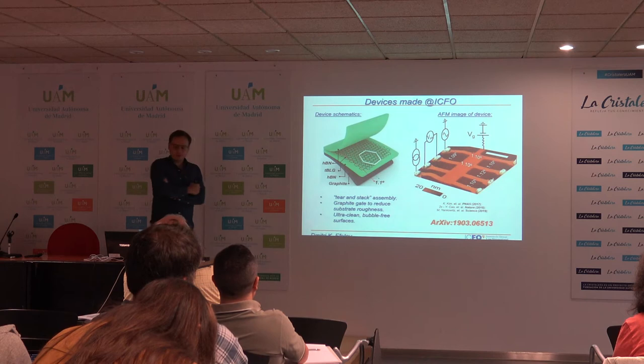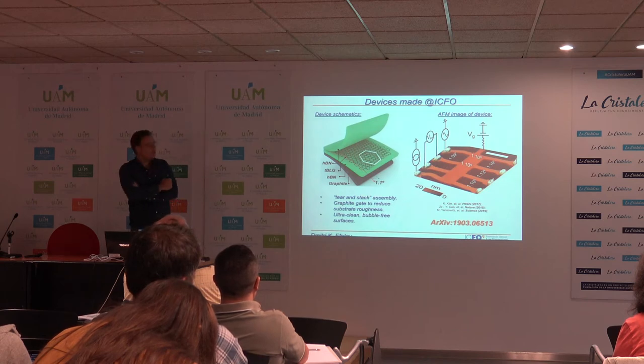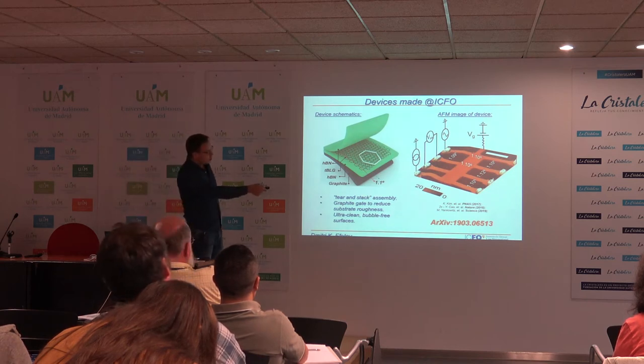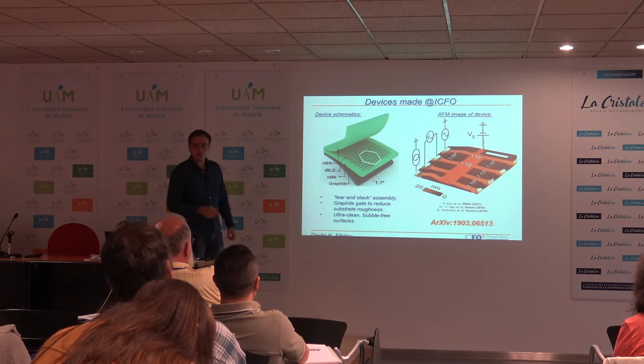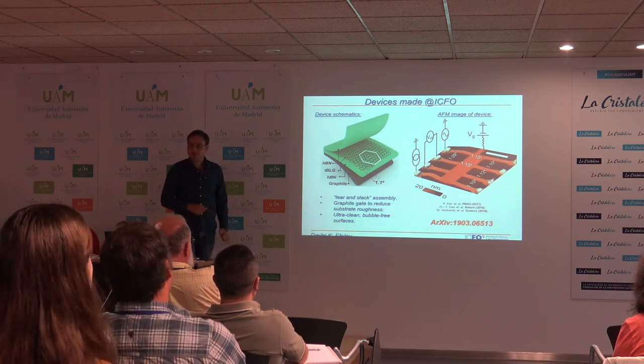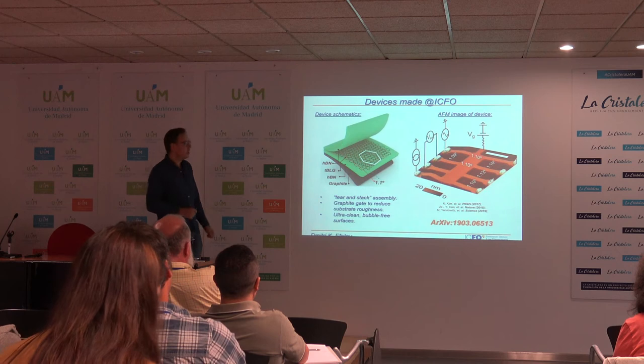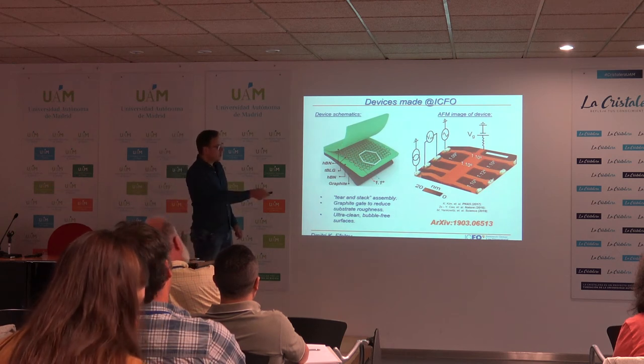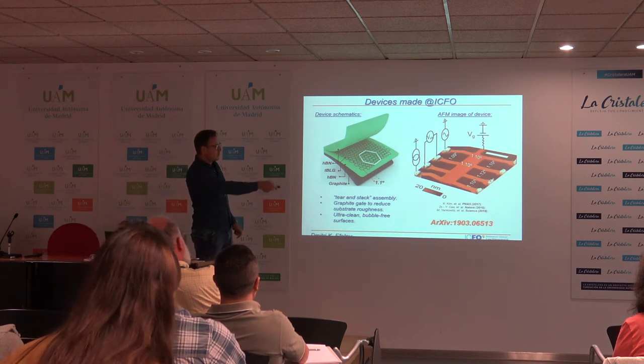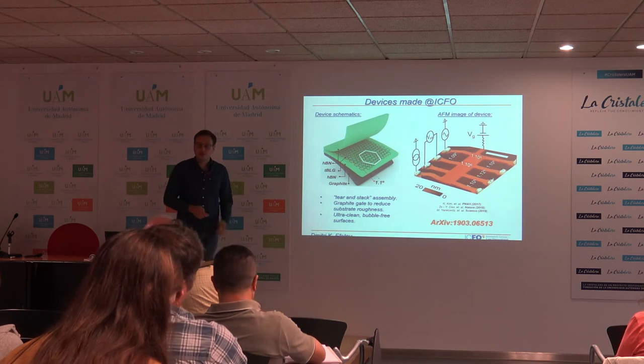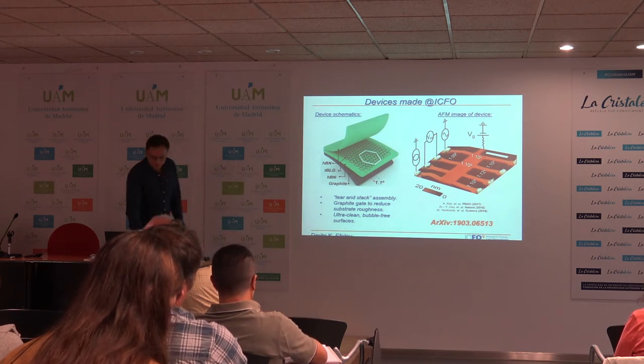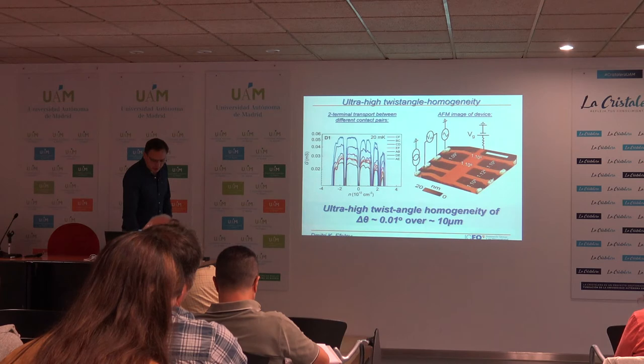You can see the AFM image really doesn't show any bubbles. It's perfectly clean, it's perfectly flat. And if we now measure the twist angle between all the contacts in the device, we really find that the twist angle is extremely homogeneous. Okay, and again, how do we measure twist angle?